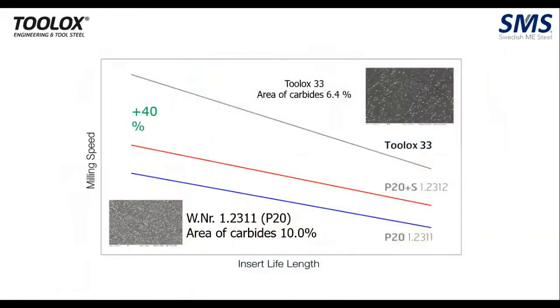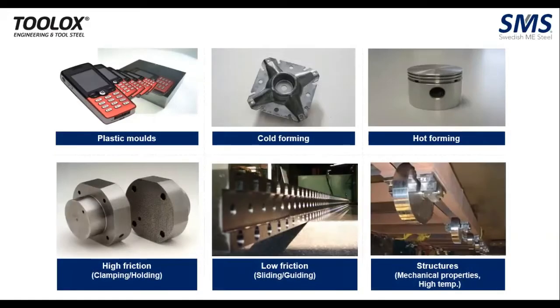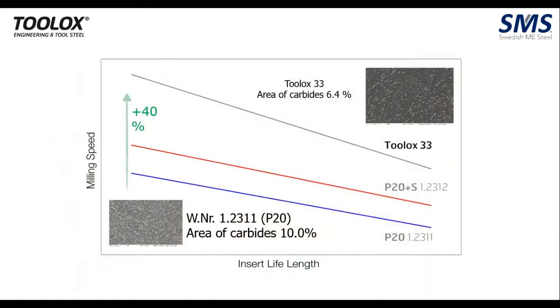So when you machine a P20 block, a normal P20, you can see that the amount of carbides is 10%, whereas in Toolox 33, it is almost half, only 6.4%. This helps you in what? If you're using the same tooling which is used for P20 for Toolox, you can either increase your milling speed by 40%, or you can keep the speed constant and increase the insert life.